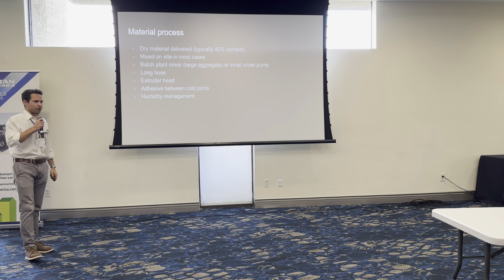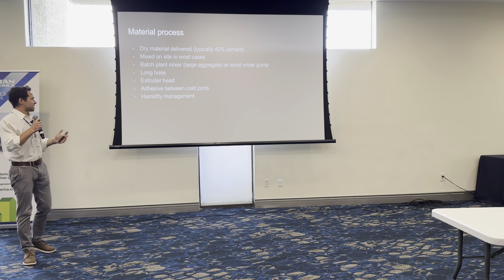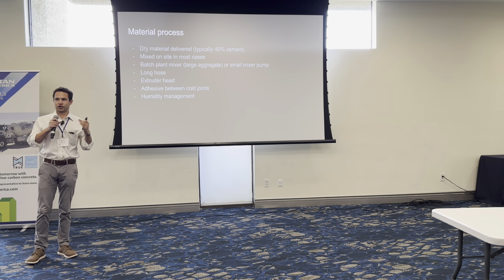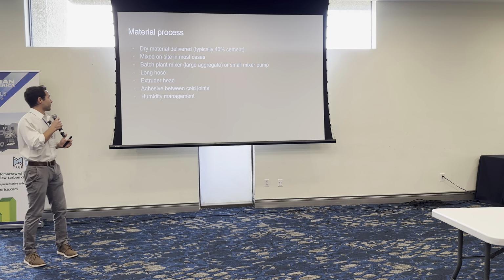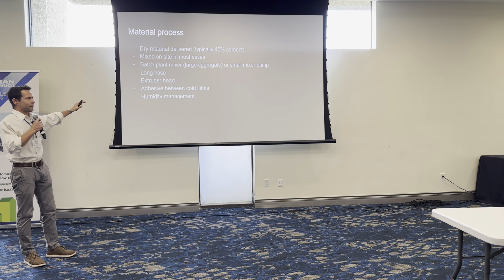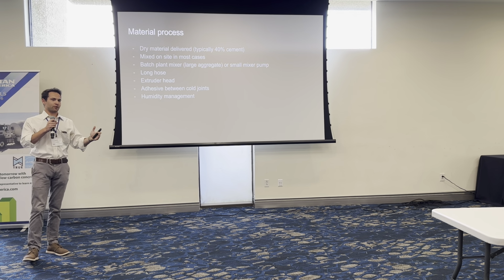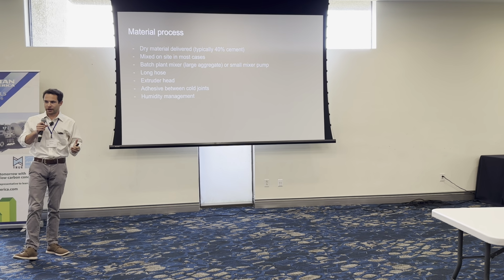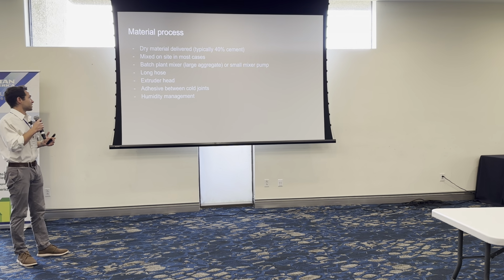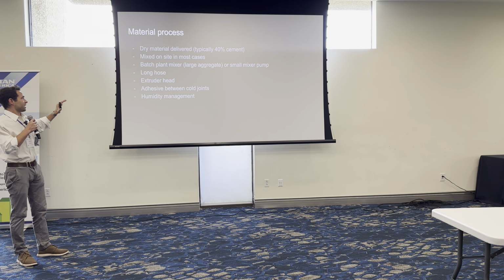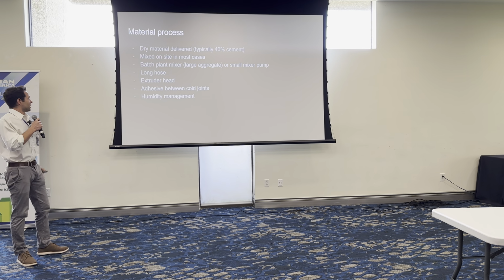Let's talk about the material process. It's quite different from a typical concrete project where it gets delivered in a truck and poured into the formwork. Typically, they have a dry material, and this might be up to 40% cement, which is kind of a challenge, kind of cost prohibitive in many cases, because most concrete would be between 10 and 20% cement.